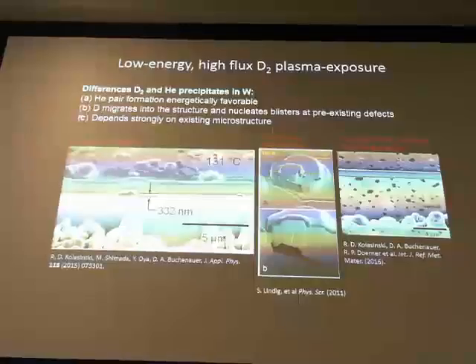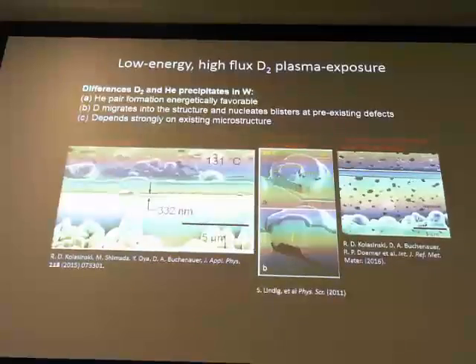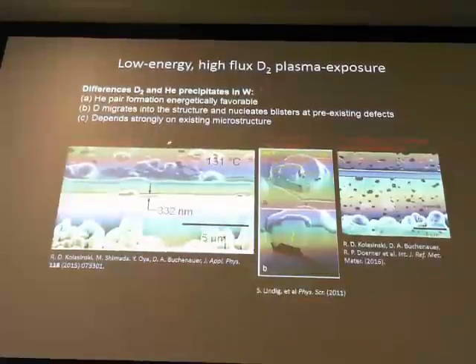Hydrogen isotopes in general migrate into the structure until they nucleate a defect at some pre-existing extended defect, maybe a dislocation loop or a grain boundary, and then the growth of that structure depends strongly on the existing microstructure of the material. You can see a few different examples of that. These are essentially focused ion beam profiles of the surface, where we're looking at an angle at what that surface morphology looks like.